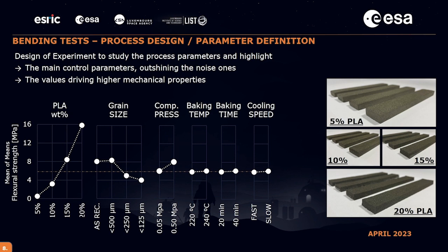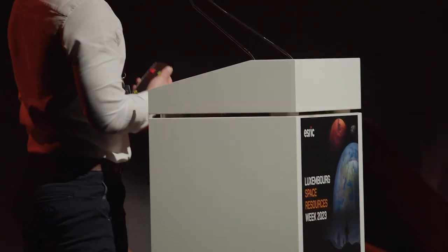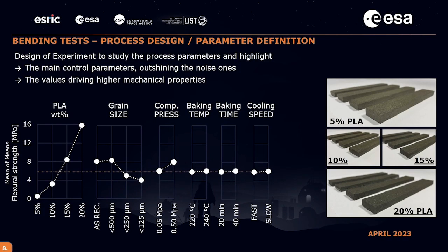We wanted to go a little bit more into the details of the process. We tried to understand how the process parameters could influence the mechanical properties, and we also wanted to study the flexural properties of the samples. So in this slide, I'm showing you the results of the design of experiment activity we performed. We are talking about 16 samples, which were manufactured with different combinations of process parameters, and they were then repeated a certain number of times, so to have a result which had a meaning from the statistical point of view. We considered the binder weight percentage, the grain size of the particles, the compression pressure, the baking temperature, the baking time, and the cooling speed.